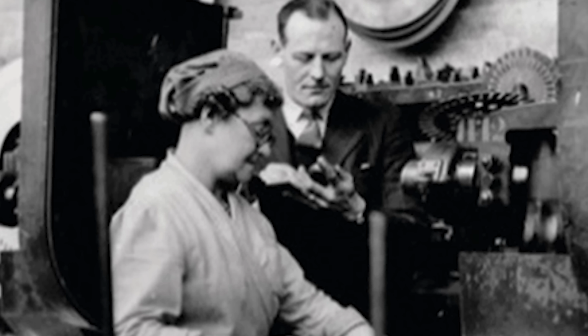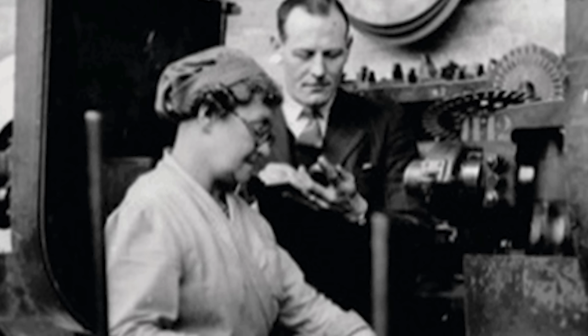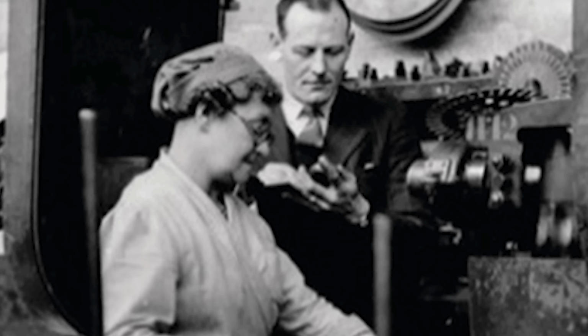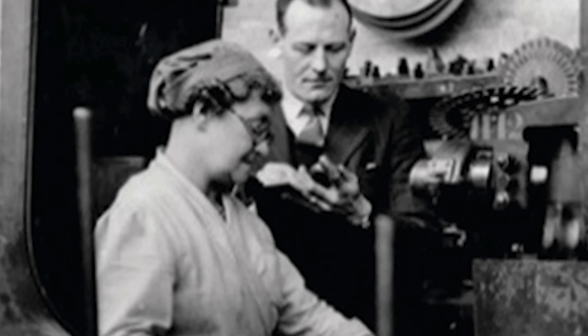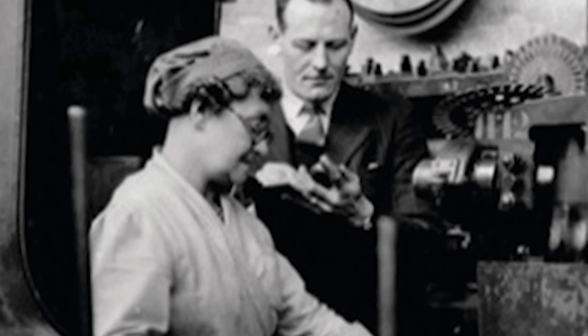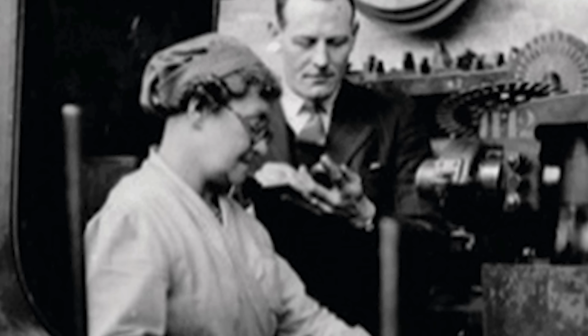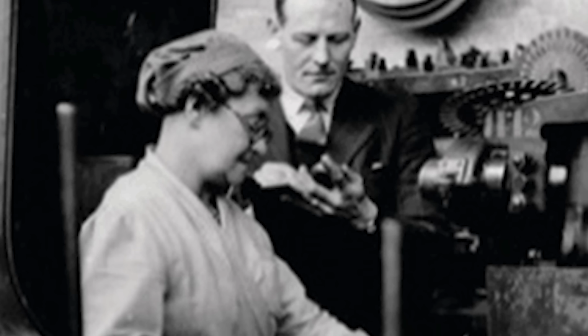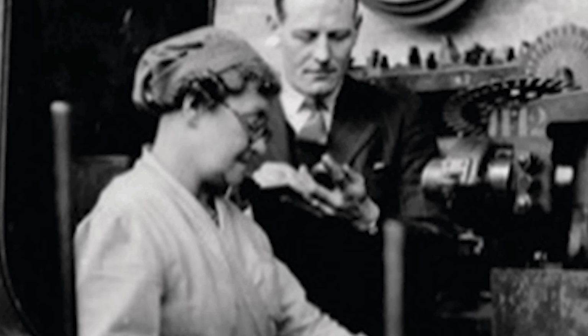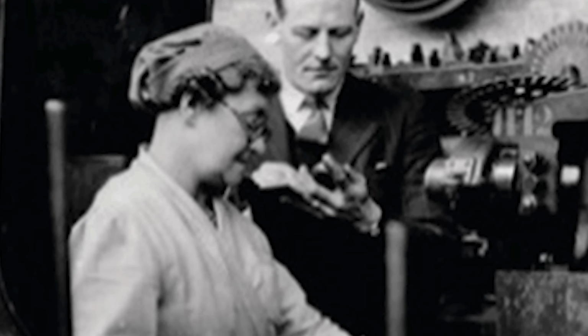Yet Taylor refused to interpret the August setback as fundamental invalidation of his approach. His engineering mind focused on understanding exactly why the failure had occurred and what operating conditions would prevent similar catastrophes. The tool had not failed because red hardness was impossible, but because it had been applied inappropriately to cutting operations that exceeded its design parameters. Working with Norwegian mathematician Carl Barth, Taylor began developing precise operating guidelines that would define safe applications for high-speed steel. Continuous cuts at sustained high speed, rigid machine setups to minimize vibration, specific feed rates that maintained constant tool engagement. Most importantly, they recognized that Taylor-White steel excelled in applications where heat was the limiting factor, not in operations where shock resistance was paramount. The failure analysis transformed Taylor's understanding of what he had discovered.